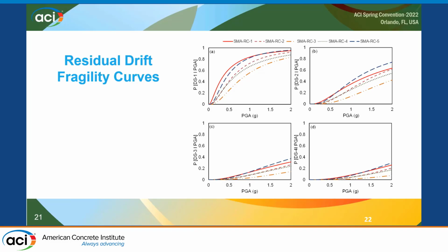And from this figure, we can also see that none of the bridge piers showed a 50% probability of exceeding damage state 2, that is shown in figure 2. And we designed the bridges for damage state 2, so that's why I'm mentioning this here. And we can also see that the bridge piers are performing according to the design performance criteria.